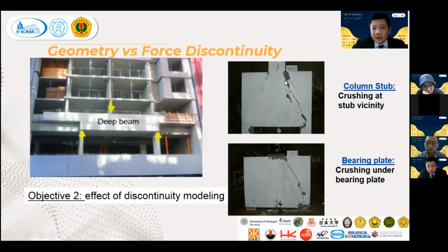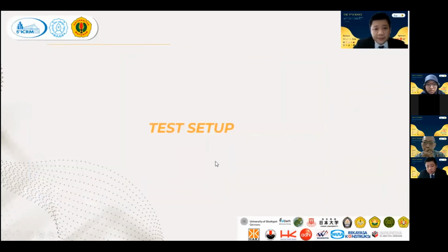However, in the literature, we often see that researchers load the force using a bearing plate. And if they use the bearing plate, then the discontinuity changes from geometry to force discontinuity. And it also affects the behavior somehow. As we can see here, the crushing shifted from the stub vicinity to under the bearing plate. Therefore, our second objective is to study the effect of discontinuity modeling.